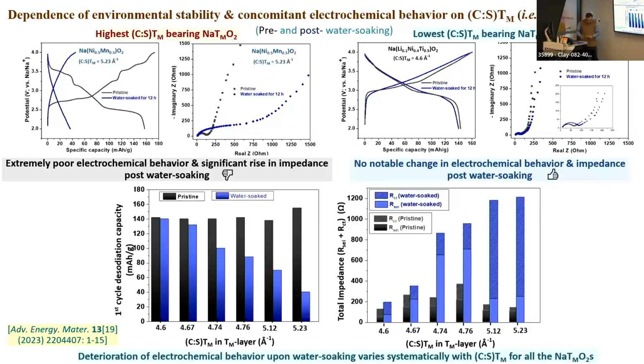So that kind of proves the hypothesis, and it gives a descriptor that, okay, by selecting or engineering the cation combination in the transition metal layer of these layered sodium transition metal oxides, I can improve the air water stability to a significant extent, which will be very important for practical usage. And this charge to size ratio can be a good descriptor for the same.